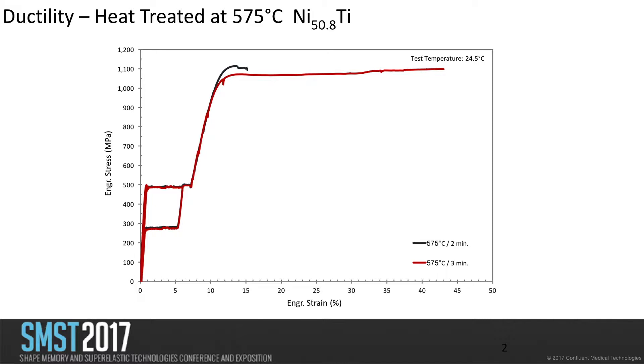As you can see, these are the mechanical properties during tensile testing of the nitinol alloys with the nickel-rich composition of 50.8 atomic percent. This alloy was first aged at 575°C for two minutes — shown as the black curve — and it was fractured at around 15% fracture strain. We did the same material aged at 575°C for three minutes — only one minute different — and it went to around 45% elongation at fracture strain. It was very interesting to see that with only one minute difference we observe this change in mechanical properties and elongation.